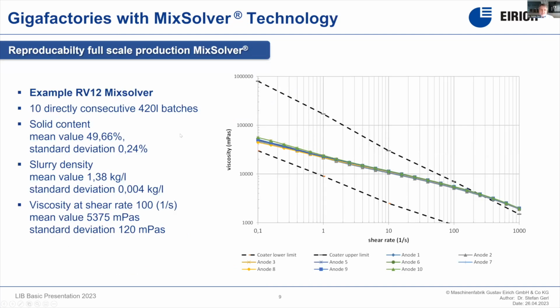This graph is now showing, out of a full gigafactory scale, a 5 gigawatt-hour factory in Asia, how good the reproducibility of our system is. We made for the SAT 10 directly consecutive 420-liter batches. And you can see that the mean value for the solid content is quite low. The standard deviation is quite low. This is mainly attributed to the dosing system, either the powder dosing or the liquid dosing. The same is true for the slurry density, because this is mainly affected by the dosing system, like the solid content. And the viscosity is also in a very narrow range. The upper and the lower black lines are the typical upper and lower limitations of the coater. We are sitting in between, and we have an excellent reproducibility batch by batch.